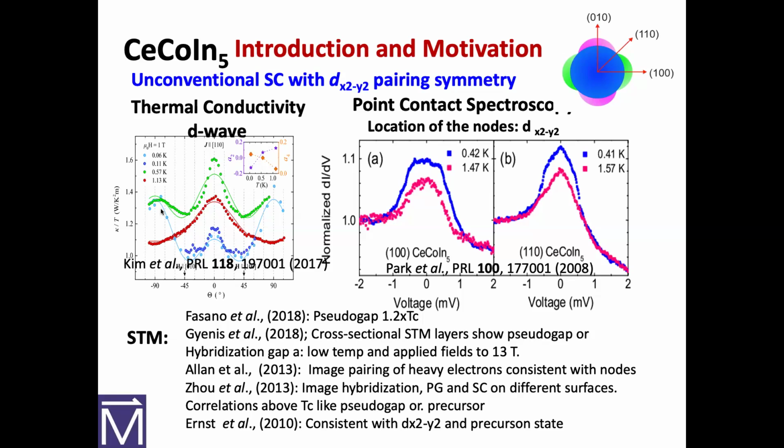And when you have the Andreev reflection, what happens is it's a very well understood, not surprising phenomenon. You shoot an electron into a superconductor and it retroreflects a hole, which means if you send one electron in, what you measure is basically two electrons out, right? A retroreflected hole looks like an electron, et cetera. So you typically get twice the conductance.